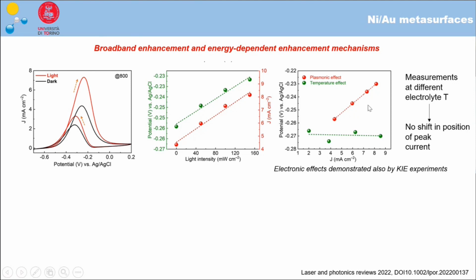And as you can see, for example, from this picture, if we monitor the potential at the peak of oxidation, we can see that changing only the temperature in the reaction medium basically doesn't change the peak position and the peak potential position in the cyclic voltammetry curve, but in the presence of light, you can see that you have a monotonic shift of this peak, and so this is basically an indication that we are driving the reactions with hot carriers.